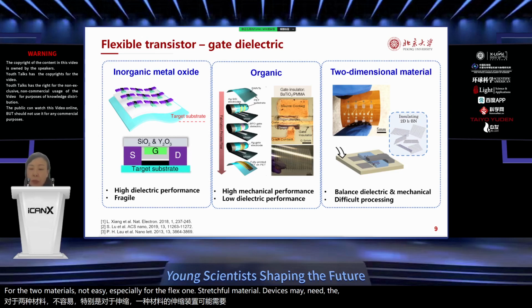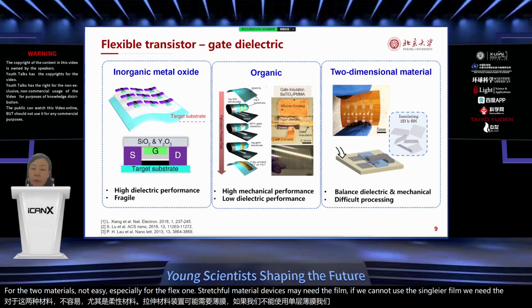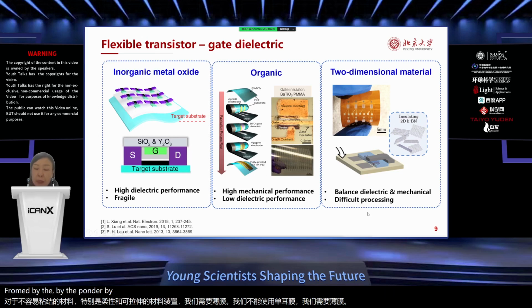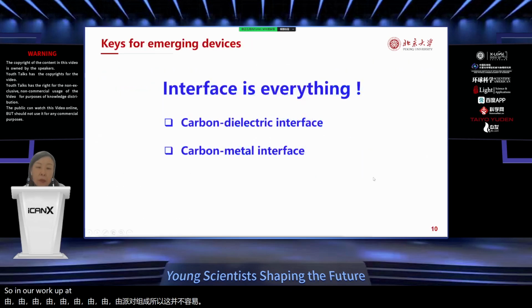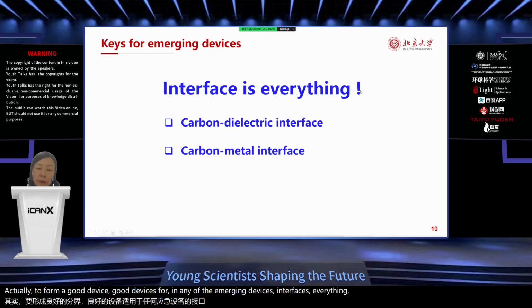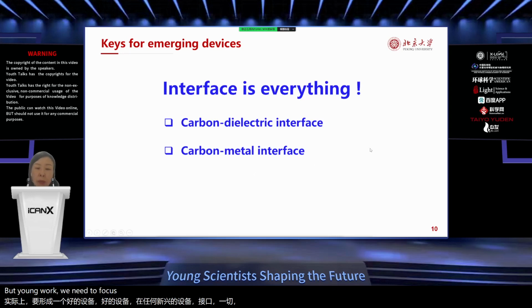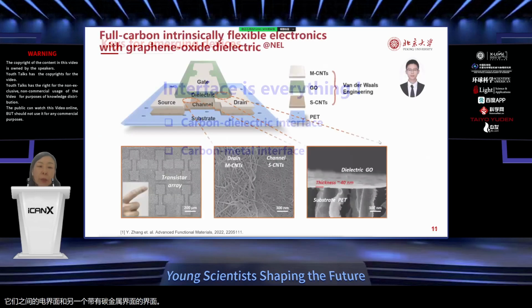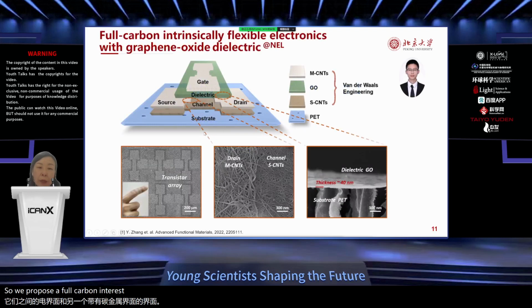We need the film. We cannot use the single layer film. We need the film formed by the powder, by the particle. So it's not easy. So in our work, to form a good flexible device, actually to form a good device for any of the emergent devices, interface is everything. In our work, we need to focus on the carbon nanotube active layer and the dielectric, the interface between them, and the other interface is the carbon-metal interface. So we propose full carbon intrinsic flexible electronics.